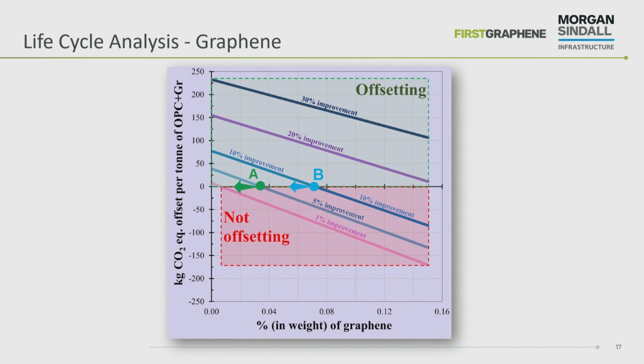So the university also looked at, now that we've got this very high CO2 footprint of the graphene and a moderate CO2 footprint comparatively for the cement, is there actually a point where you can add graphene and still get a CO2 benefit? So yes, dependent on the strength improvement and the amount of clinker you can reduce in your cement. The target of the project was to produce a CEM2, a limestone cement with a 52.5 N strength class. So it was trying to improve the existing 42.5 N strength class up to 52.5, and then that could start to replace some of the applications where a CEM1 was used.